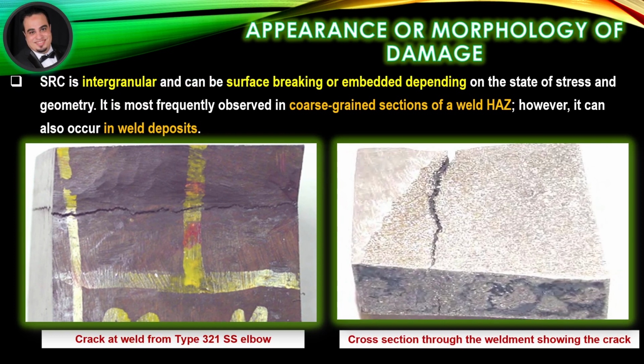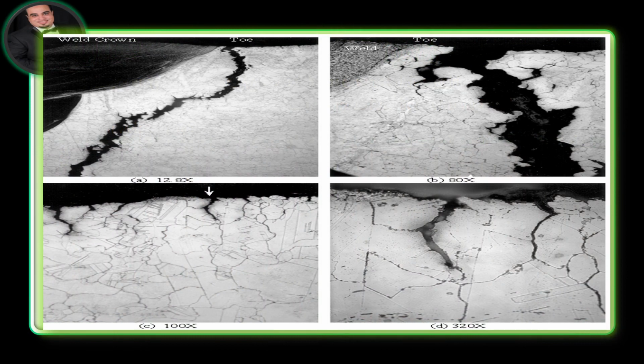Appearance or morphology of damage. Stress relaxation cracking is intergranular and can be surface breaking or embedded depending on the state of stress and geometry. It is most frequently observed in coarse-grained sections of a weld HAZ. However, it can also occur in weld deposits, as illustrated in the figures: crack at weld from type 321 stainless steel elbow, and cross-section through the weldment showing the crack. Photomicrographs of the weldment area.